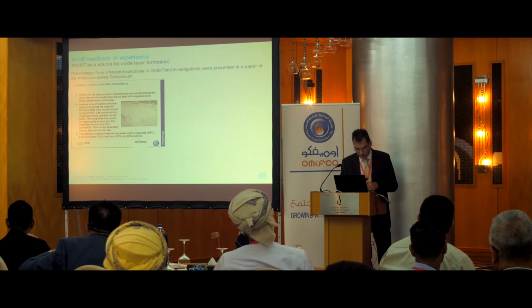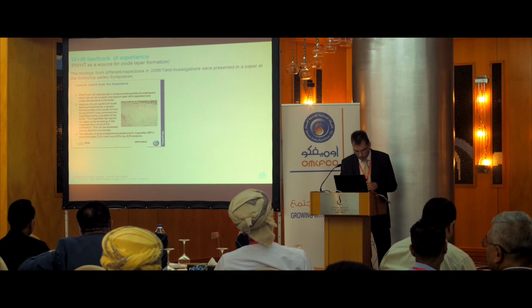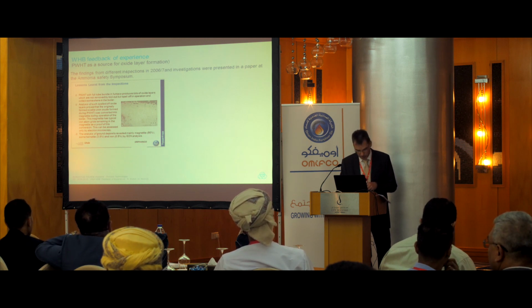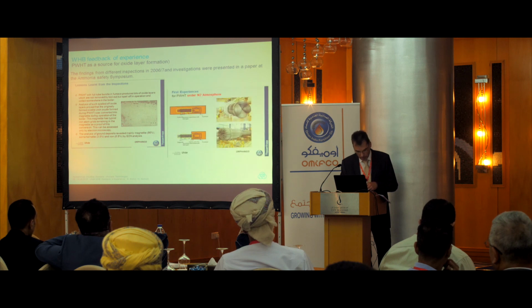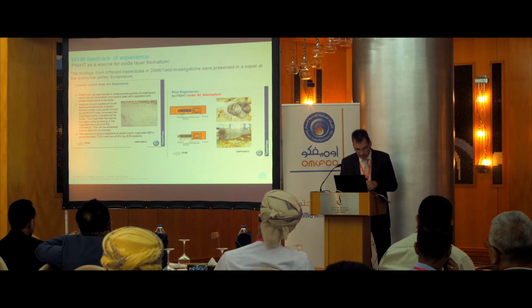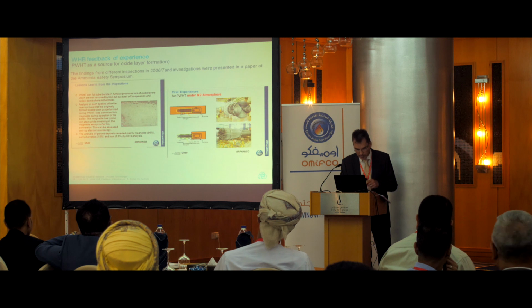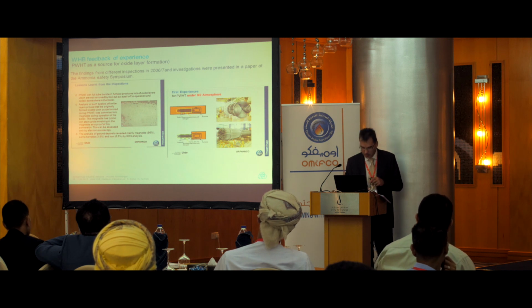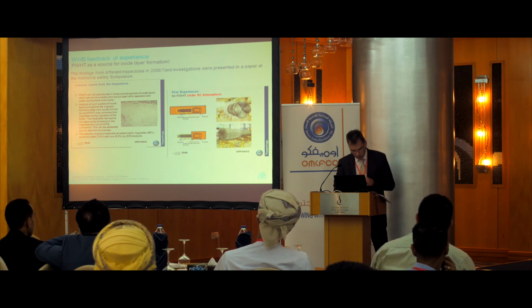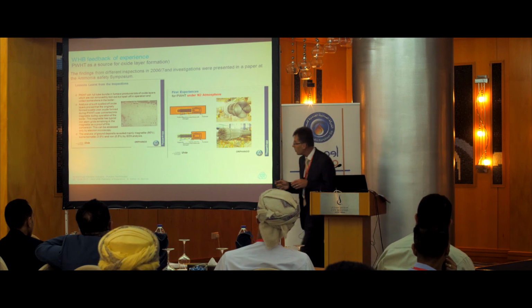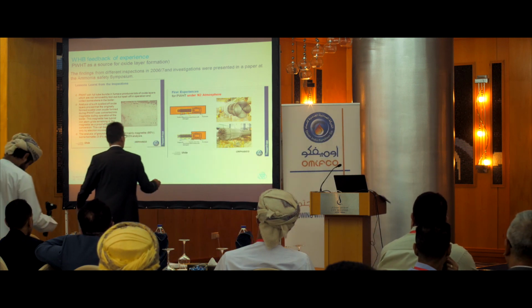As it was not really possible to flush out completely spalled-off oxide layers or remove them during initial boil-out, the logical solution was to prevent its formation during post-weld heat treatment. Thus, all post-weld heat treatment in Uhde waste heat boilers were done since 2007 with an auxiliary shell. This is shown on the right side. I hope you can see the yellow.